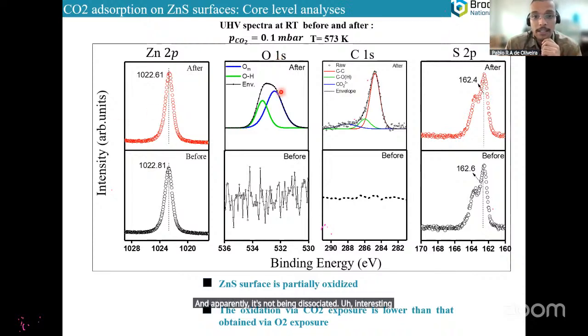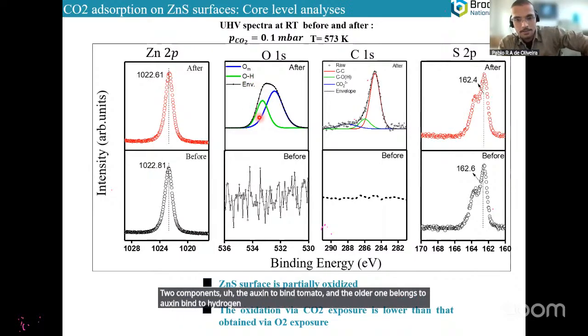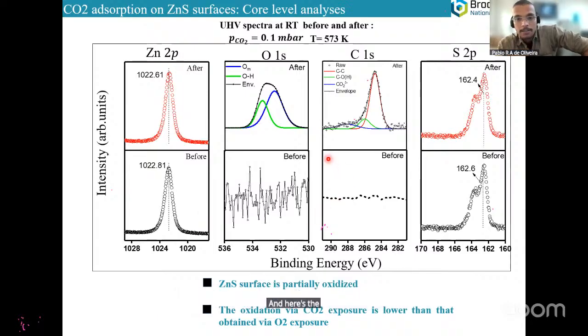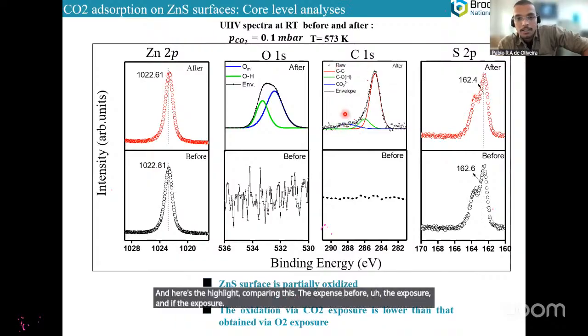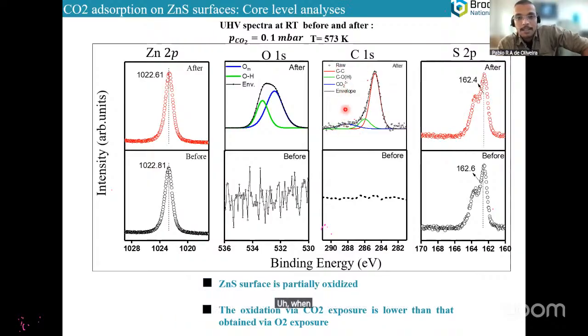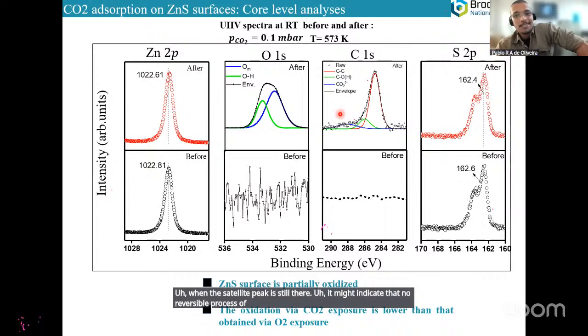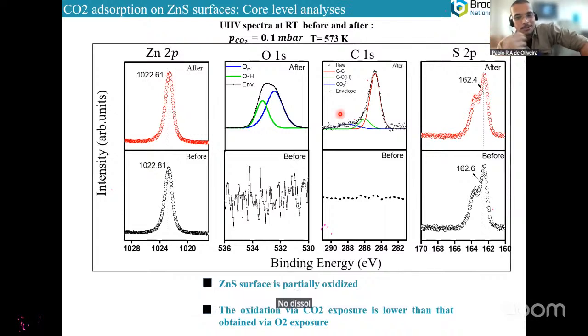Interestingly, the oxygen peak revealed to us, after UHV, two components: the oxygen bound to metal, and the other one belonging to oxygen bound to hydrogen, as you said before. And here's the highlight comparing the experiment before the exposure and after the exposure, where the satellite peak is still there. Which might indicate a non-reversible process of non-dissociative CO2 reduction adsorption on ZnS.